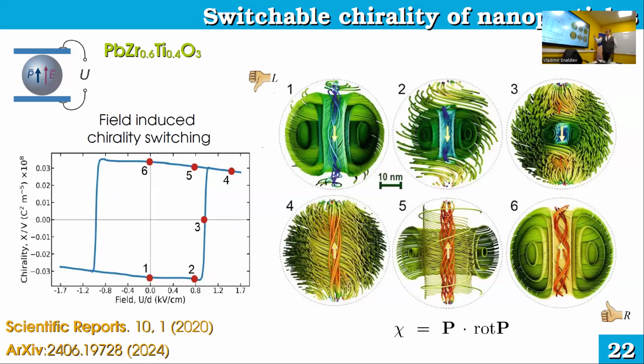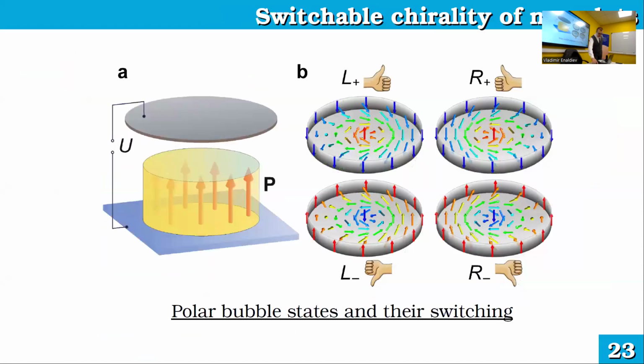And what's interesting, going through this, switching this nanoparticle with electric field, you can really switch chirality from left to right. And you can distinguish the states, for example, with left and right polarized light. So here we can see switching between two different states. But in nanodots, we found the possibility of switching between 4 different chiral states. Because chirality, based on this description, cannot be only left and right, but also plus and minus. You can use the right-hand rule and see the direction of the rotation vector with 4 fingers and with some directional vector in the center.